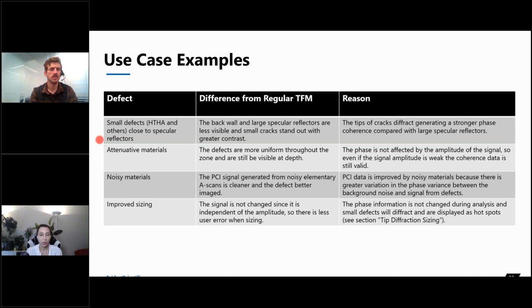Also for attenuative material, and by this one we can talk about stainless steel, we'll talk about that in the next point, but also for very thick components. So that's a problem for UT or conventional UT, conventional phased array, conventional TFM. When we look at the amplitude, we are often going to lose a lot of that sound in the part. So the defects are more uniform with PCI throughout the zone of the part, and they are still visible at a great depth because, again, we're not looking for an amplitude, we're looking for a diffraction. So the phase is not affected by that amplitude loss of the signal, and so even the signal amplitude that is weak in the coherence data is still valid and shows up very nicely.